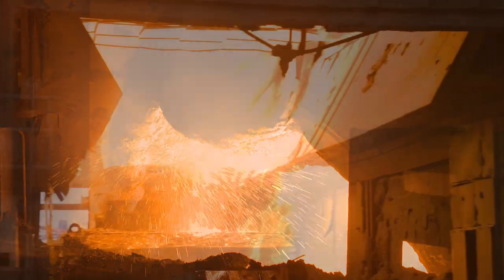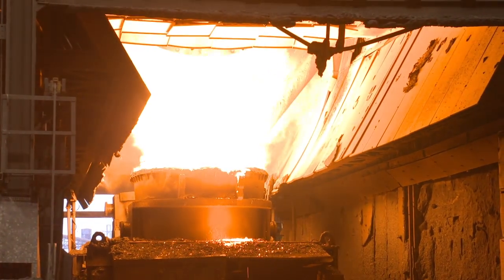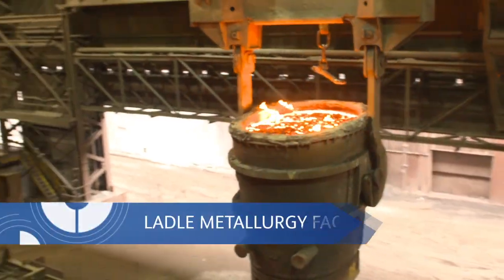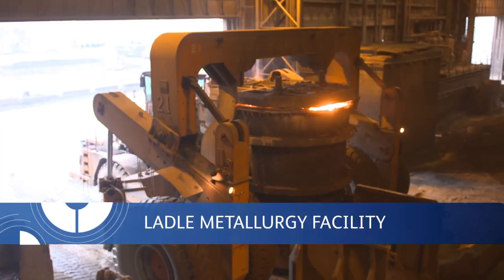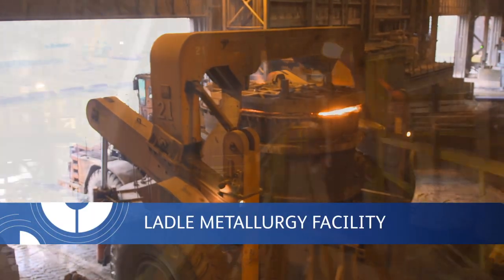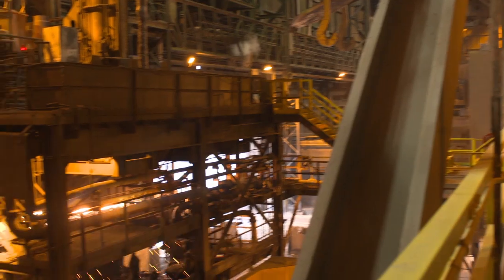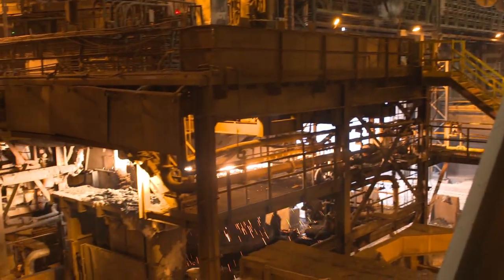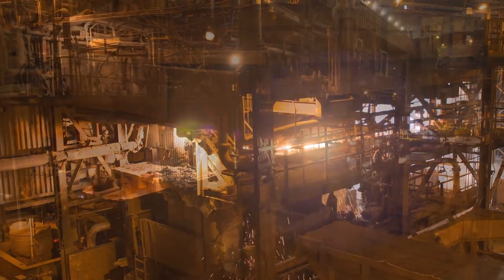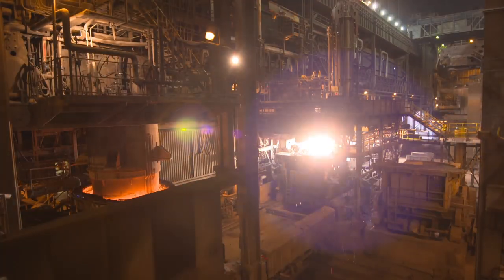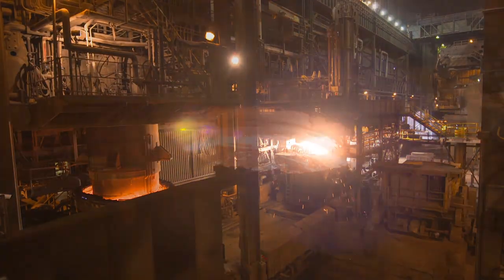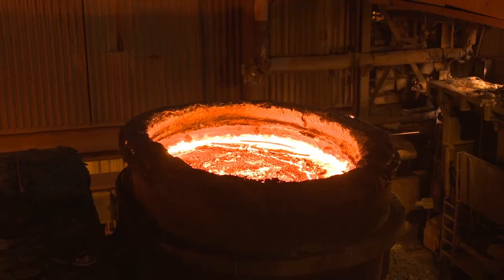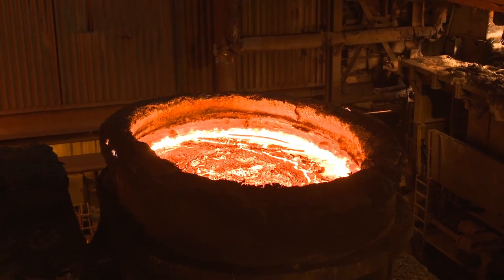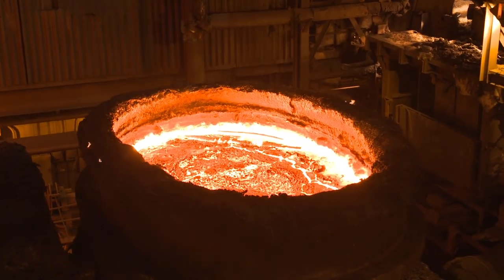The BOF vessel's molten steel contents are poured into a ladle capable of carrying 250 tons and brought to the LMF, or ladle metallurgy facility, where precision chemistries are produced. Electrodes are lowered into the ladle and the liquid steel is reheated while alloying elements are added to achieve the chemistry required by the customer. The process controls the chemistry, cleanliness, and temperature of the steel.